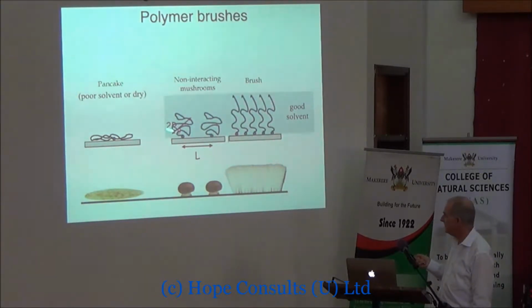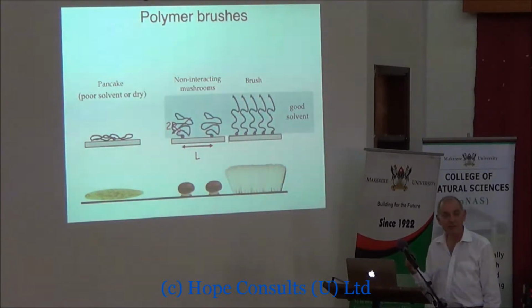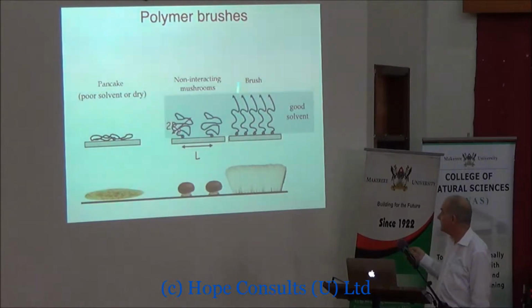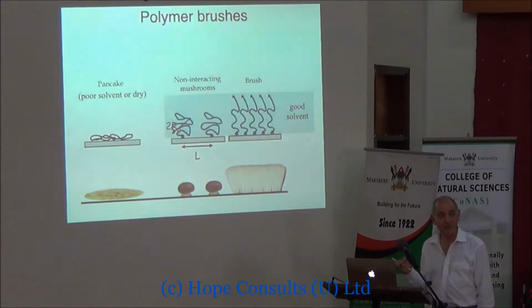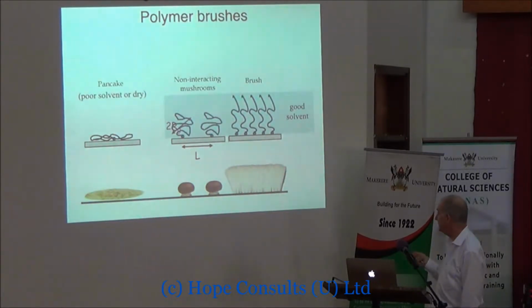But as they get closer and closer together, they want to keep out of each other's way because there's an entropic penalty if they start to interact with each other. To avoid that, they stretch out into the solution against the elastic forces, and they become what's called a polymer brush. So you have a whole load of polymer chains that are really stretching themselves to have as much interaction with the solvent as possible and as little interaction with each other. This is all driven by a combination of entropic and enthalpic forces, but mostly entropic forces. And this is what we call a polymer brush. These chains can be any length, but typically they're between 10 and 1,000 nanometers long.